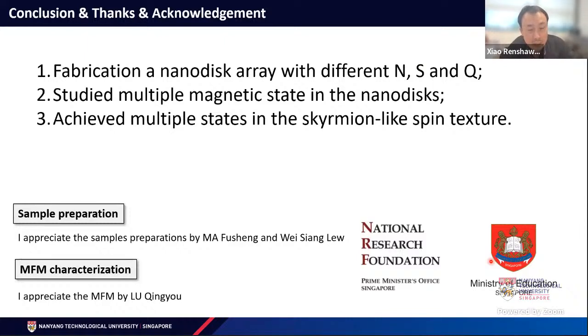So we fabricated the nanodisk array. We play with mainly the N, S and Q, and also we studied the multiple magnetic states in the nanodisk, and we achieved different states in the skyrmion-like spin textures. And they're stable when we play with the magnetic field. They're stable within the magnetic field window.